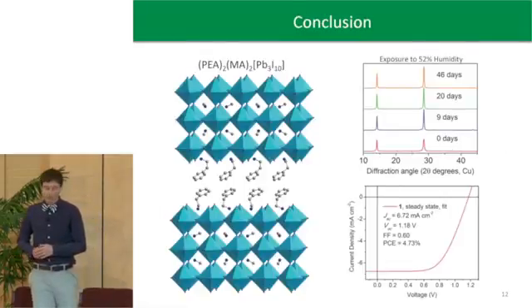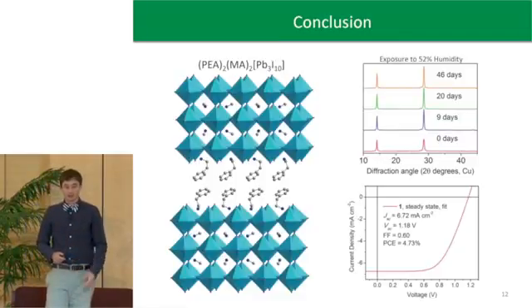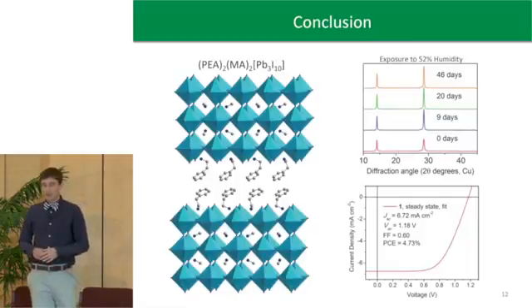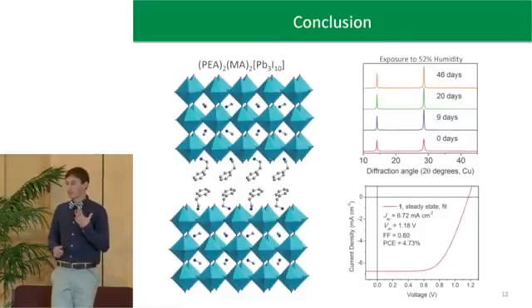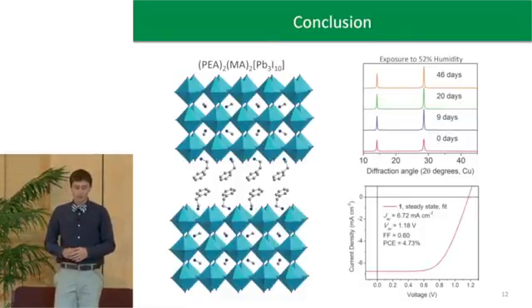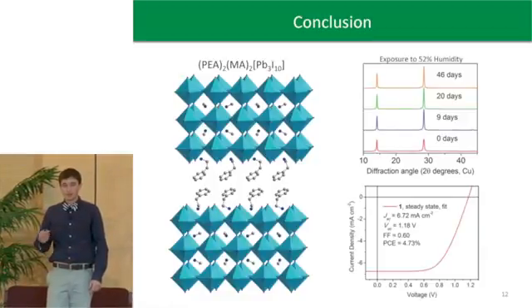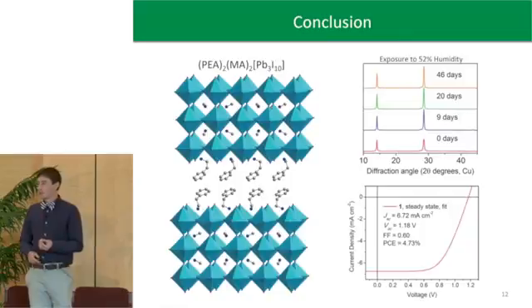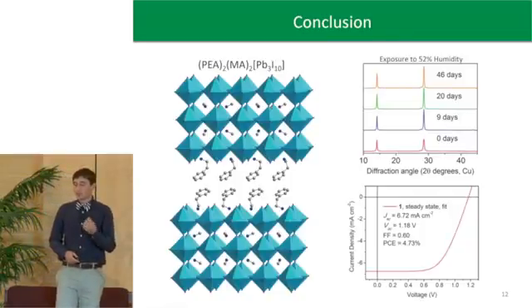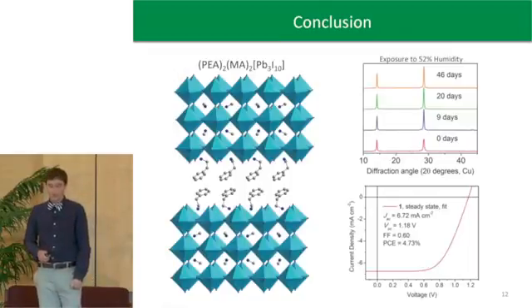So with that, I'd like to conclude by reiterating that I was able to make this new material. I didn't say this before, but this is the first N=3 lead iodide perovskite ever reported. We were able to test the humidity stability of this material, and we show that it is much more robust when you expose it to a controlled humidity environment compared to the 3D perovskite. But also, putting it in a device, it performs very well, especially as a first-generation material, getting almost 5% efficient conversion of the solar energy.